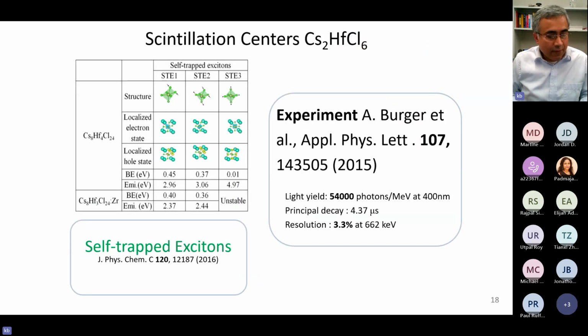Then we went on to find out the mechanism of those emission centers, how that emission can happen, and for that we isolated different structures. We call them STE1. STE means self-trapped exciton, an exciton that traps by itself. And remember, what is an exciton? It's a trapped hole and a nearby trapped electron together forming the self-trapped exciton. We found at least three different types of structures, and we can find out their binding energy, meaning how stable they are.